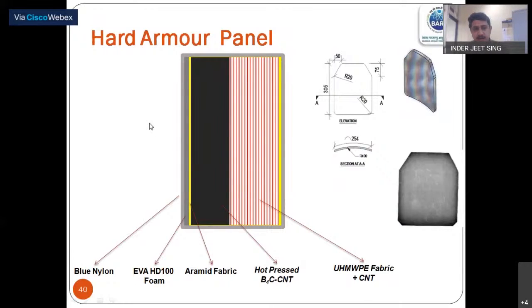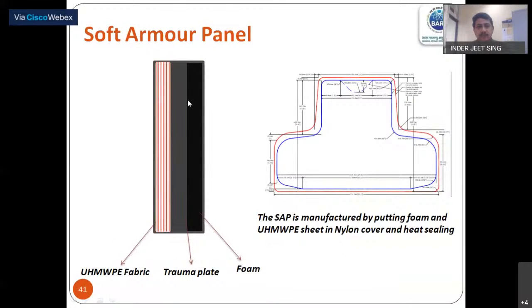Initially, the hardness of the front face should be more than the hardness of the bullet, so it should blunt the bullet and fracture it. In that way the ceramic itself gets fractured and the bullet is also fractured. The backing material, that red color you can see, is the layered structure of carbon nanotube and ultra high molecular polyethylene fabric. Their role is to contain the bullet fragments as well as the ceramic fragments, so that they don't become secondary bullets. And what is the role of the soft armor panel? The soft armor panel absorbs the other energy, so it gives you the cushioning effect as well as reduces the trauma on your body.